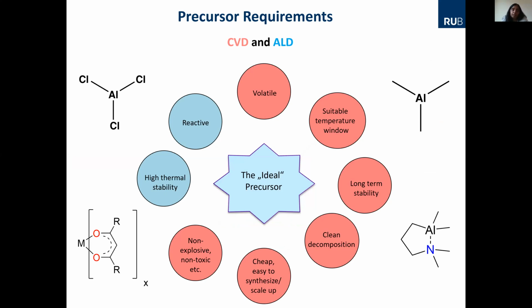So as a chemist, one can say, okay, I make some molecules in the lab, and a material scientist would then say, I will test it in the reactor, whether it works for CVD or ALD. But before that, one has to see whether this molecule we buy or synthesize in the lab should be volatile. That means you should bring it into the gas phase without decomposing. So it can be aluminum trichloride, which can be commercially bought, or you can think of trimethyl aluminum. This also is a very pyrophoric compound, but can also be commercially bought. They are very volatile. Then they should be reactive to the substrate surface as well as to the co-reactant.